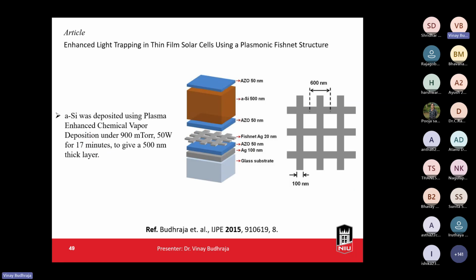In another research article, Enhanced Light Trapping in Thin Film Solar Cells, we published this article in 2015, and we used the plasmonic fishnet structure in the film growth of amorphous silicon. So this is a stack of AZO and a-Si, that is the aluminum-doped zinc oxide and amorphous silicon, and this is a transparent film. So the application is in thin film silicon solar cells.